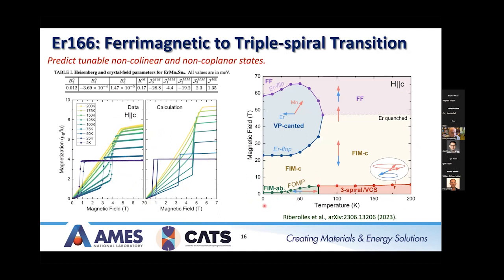magnetization process, where you're going from ferrimagnetic in the AB plane, if you look over the phase diagram here, to ferrimagnetic in the C direction. And then as you warm up into this triple spiral phase, this FOMP basically disappears. You get more smooth linear type behavior before plateauing.